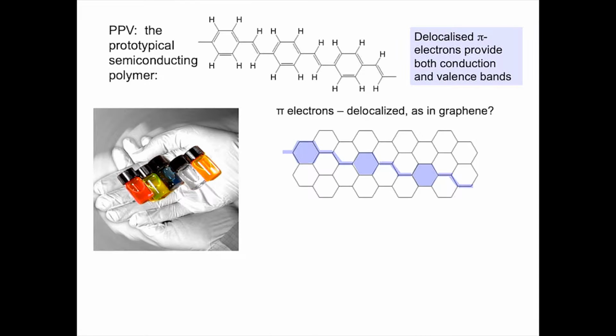There are 2 bonds to adjacent carbons, but a 3rd bond to a hydrogen for most of the carbons along the chain. And where carbon has only got 3 bonds, the 4th bond left over we sort of represent as double bonds, or we don't bother at all when we draw the structure of graphene. But those electrons are only weakly constrained, and they're not tied to one particular carbon-carbon bond. They delocalize. And because they're spread out, we can then move charge up and down or across sheets or chains of these so-called conjugated carbons.